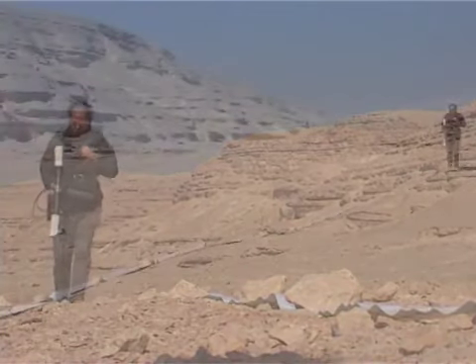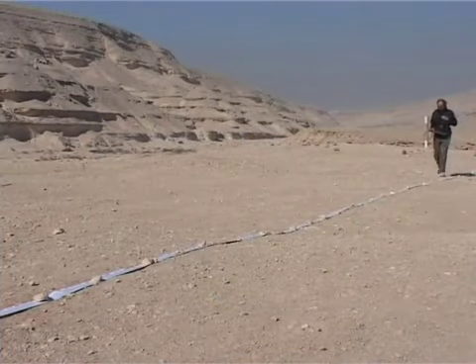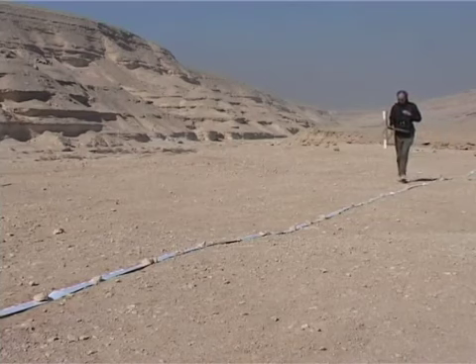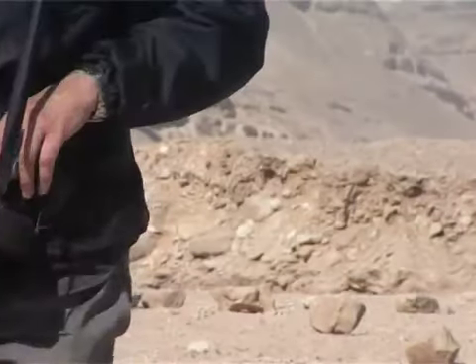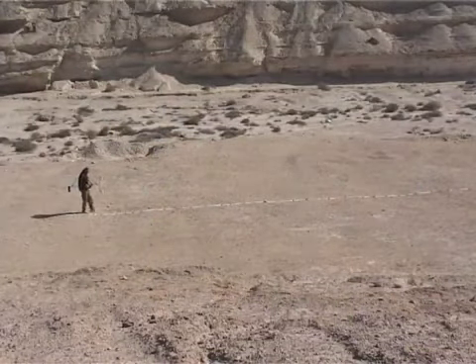How to locate the furnaces on these vast sites? It is here that geophysical surveying comes in. It is based on a simple principle. The ground has a particular magnetic field that can be disturbed by subsoil material. Now, after repeated heating, the baking of clay transforms certain iron oxides into highly magnetic minerals.